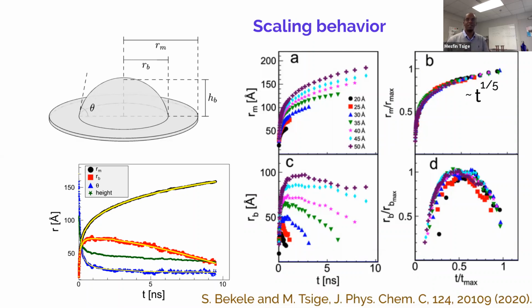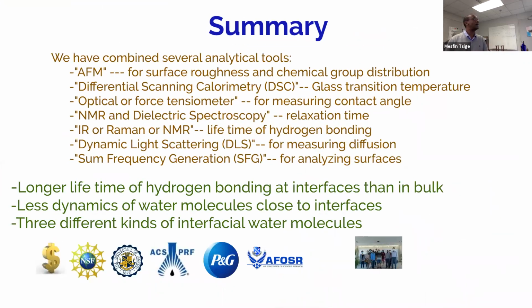So to conclude my talk, I think you may have seen that in the process of analyzing our simulation data, what we have done is similar to, let's say, measuring surface roughness. It is like using atomic force microscopy in experiments, because we have characterized the roughness of our surface. And of course, we have also determined the glass transition temperature of our polystyrene film, because the polystyrene film that we had was in a glass state. It is similar to using differential scanning calorimetry in experiments.